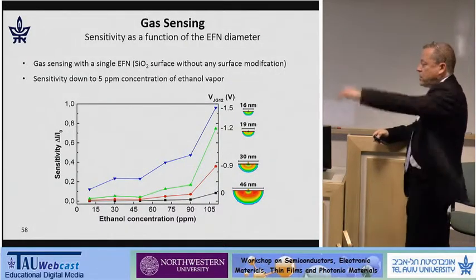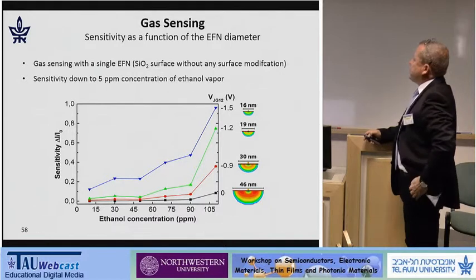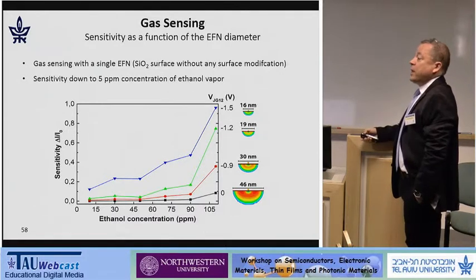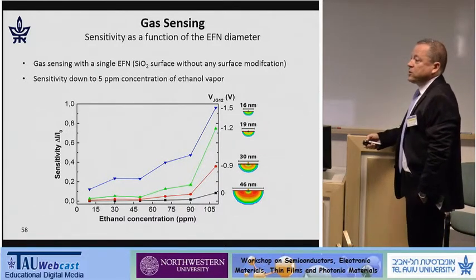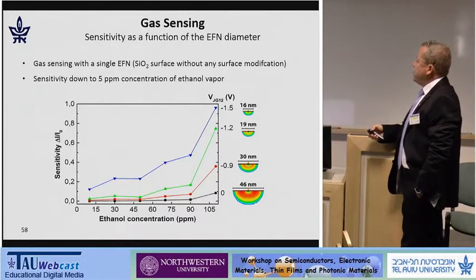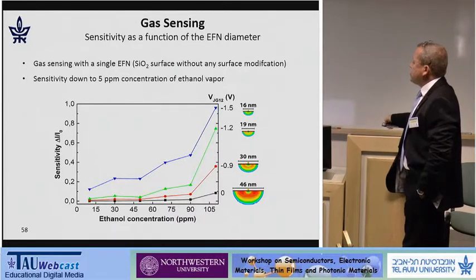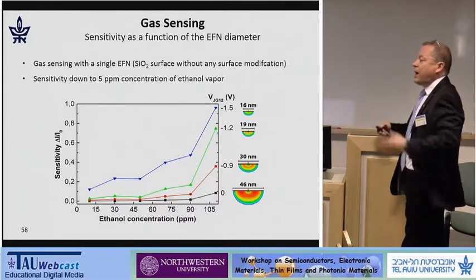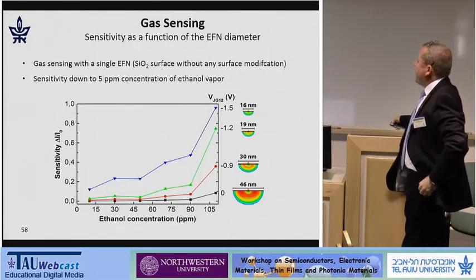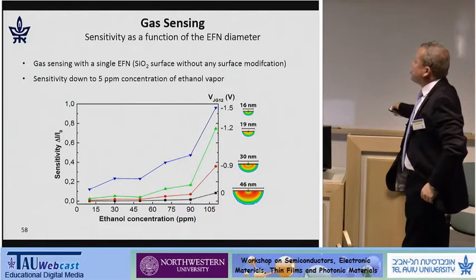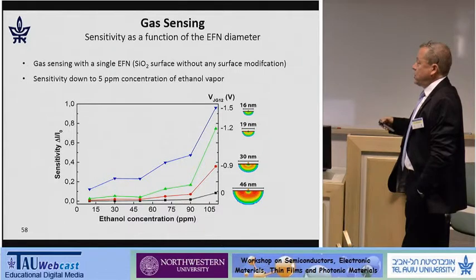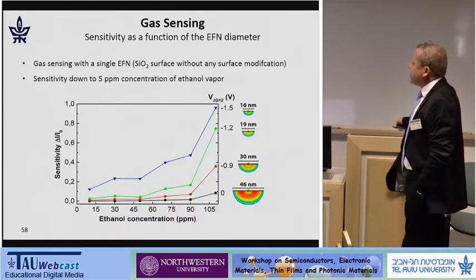Now to gas sensing. So the first gas that we wanted to sense is very simple, ethanol, because ethanol is non-poisonous and very easy to measure. And what you see here is the ethanol concentration on the x-axis and the sensitivity, which is delta I over the background current, as we reduce the virtual nanowire dimension by the negative side gate voltages. So in this specific device, we started with a fairly small nanowire.